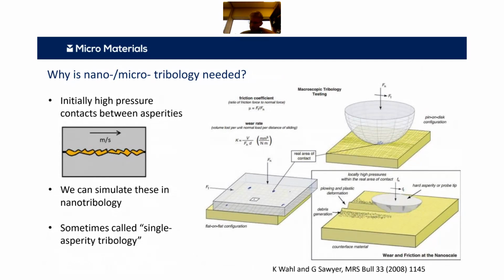So, moving on to the tribological part of the tests, essentially. If we think about tribology, a lot of tribological testing is done at a more macro scale, where there is essentially high pressure contacts between the asperities. What you're seeing is that the assumption in something like a pin-on disc test is that you can calculate an apparent contact pressure, and that is the contact pressure.